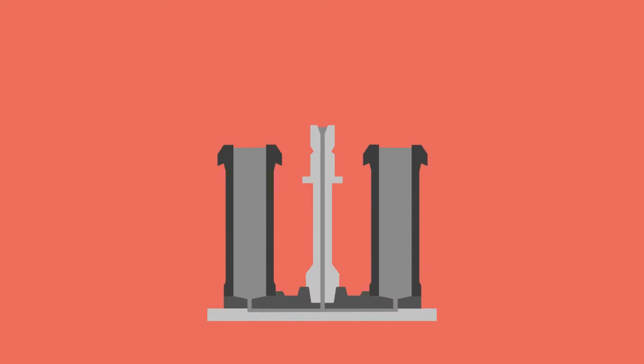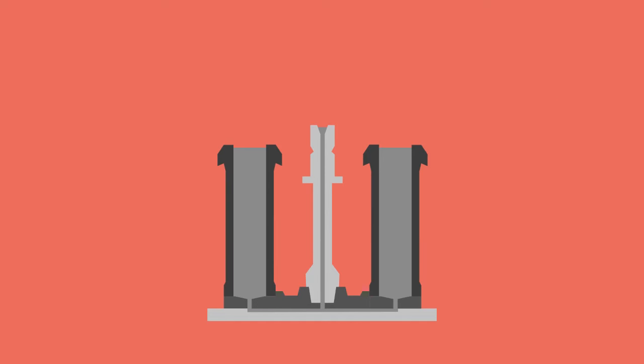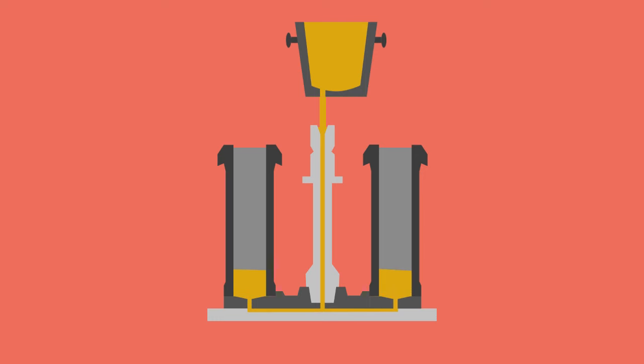Ingots that are uphill teemed use a ladle either directly or in a teeming car that is positioned over a feeder system to enable the ingots to be filled from the bottom of the mold. The ladle is positioned over a funnel called a trumpet. It is opened and the metal stream established. The pouring rate is controlled throughout this teeming process. Powders which have an exothermic reaction are often added to the top of the ingot following teeming to generate heat to aid in the feeding of the ingot, minimizing void or pipe. Insulating material is also added to aid in this.